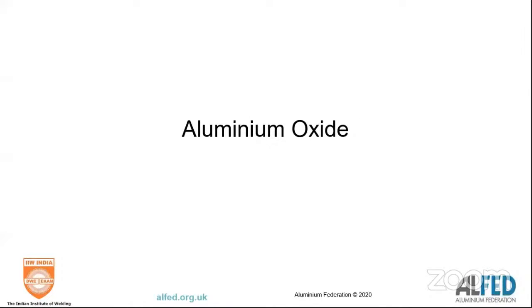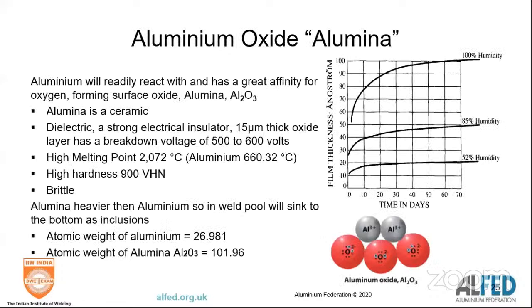Let's talk about aluminium oxide. Aluminium oxide is incredible because it imparts to aluminium the corrosion resistance that sets it aside from so many other metals. But it's alumina, aluminium oxide, so it's a ceramic. That means it's an electrical insulator. And at 15 microns, the breakdown voltage is about 500 to 600 volts. Very high melting point, about 2000 degrees C. Very high hardness, typically about 900 Vickers. It's also very brittle. One of the things you need to realize is that alumina is much heavier than aluminium. So if you've got alumina forming in a weld pool, it will sink to the bottom as an inclusion.